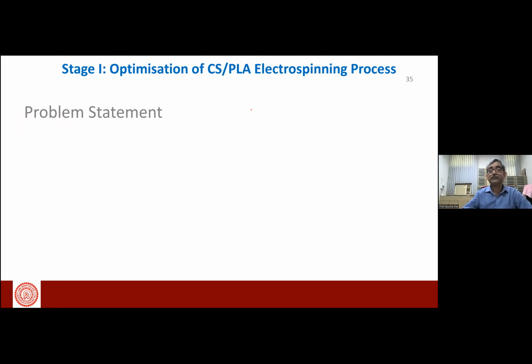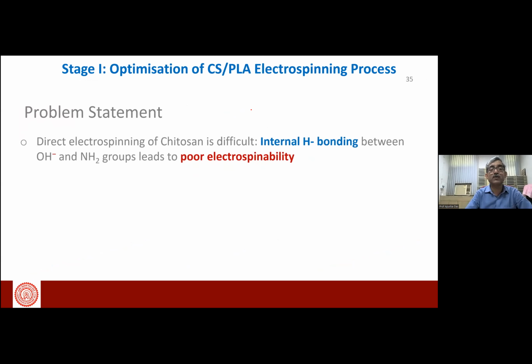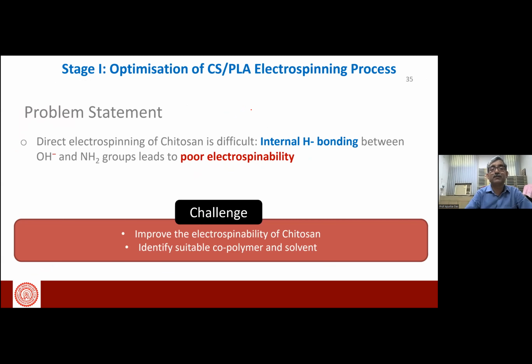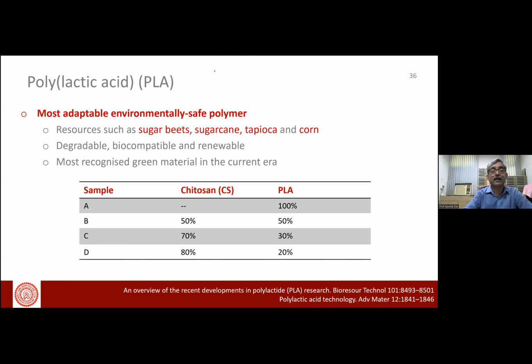And then the problem statement was the poor electrospinnability of the chitosan. We have used chitosan, as chitosan is known to be a natural antibacterial product. So to improve the electrospinnability, we have blended it with polylactic acid. At different proportions we have used: 100% polylactic acid, then 50-50, 70-30.